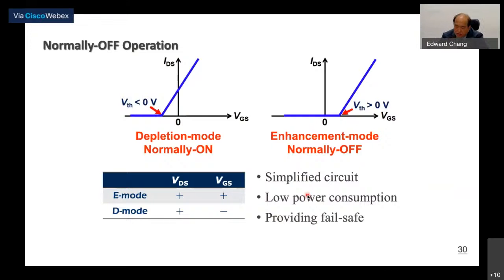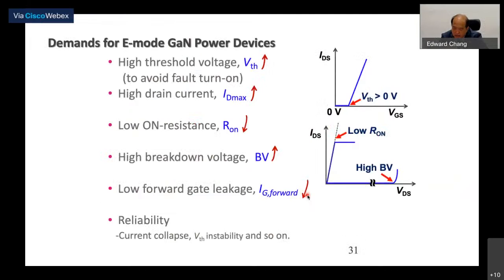safety problem. So an E-mode device provides a fail-safe approach. That's why we need E-mode devices. But even with E-mode, there are quite a lot of approaches, and the most important thing is still to have high VTH. Because even with E-mode, you can still have failure: if your VTH is not high enough and there's an accidental signal, a pulse, then your car can still be turned on. So you need high enough VTH, usually around 2.5 to 3 volts, or higher.